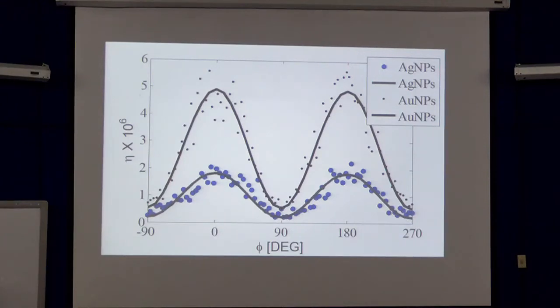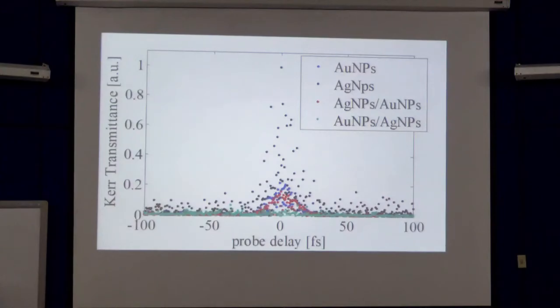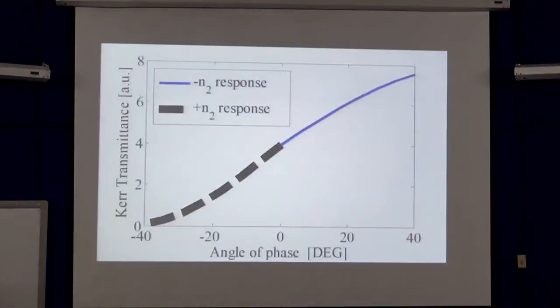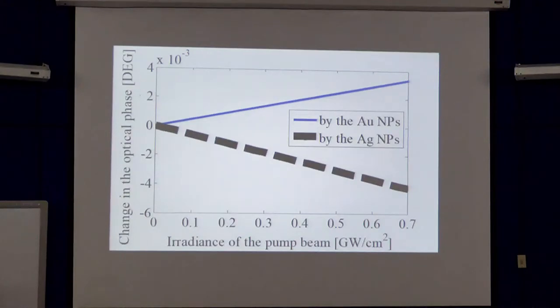And also, we can compare the response from silver and gold for the same wavelength, that is green in this case. The response when you put, this is for the blue one, this one is for gold, this is for silver. The red is when the beam impacts first the silver and then the gold, and then you can see there is no response if you change the direction of the sample. This is because they have different sign in the nonlinear refractive index, and also the phase of the beam is going to be changed by the use of different nanoparticles.